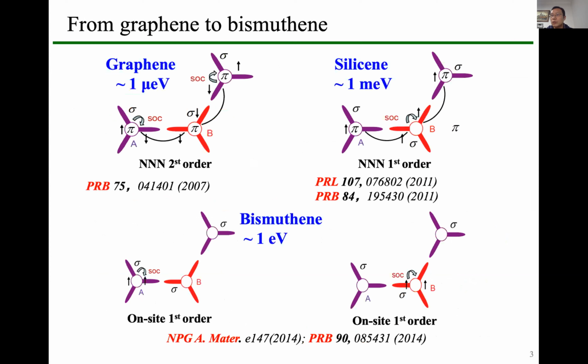Although graphene was the first material proposed to exhibit the quantum spin Hall effect, because the spin orbital coupling in graphene is very weak, the band gap is only about 1 micro eV, which is too small for any practical application or experimental observation. So in 2011, Professor Yao's group started silicene, which means using silicon atoms to replace carbon. And because silicon is much heavier than carbon, the band gap is 1,000 times bigger. So this can be a quantum spin Hall insulator.